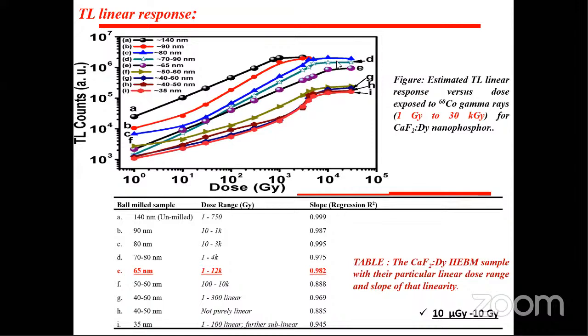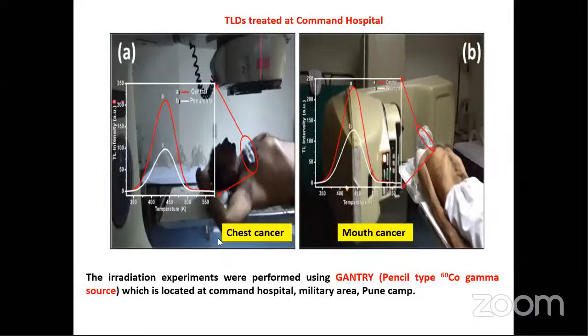This spectra indicates the 65 nanometer sample. Okay, and the standard TLD material, we can say TLD 200, shows 10 microgray to 10 gray. But now we have developed our material up to 1 gray to 12 kilogray by decreasing the particle size. Okay, so we have also put our sample onto the cancer patient and recorded